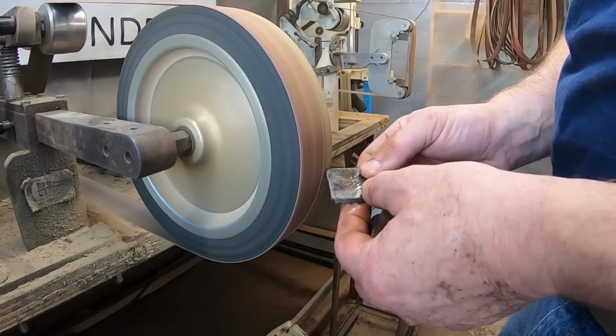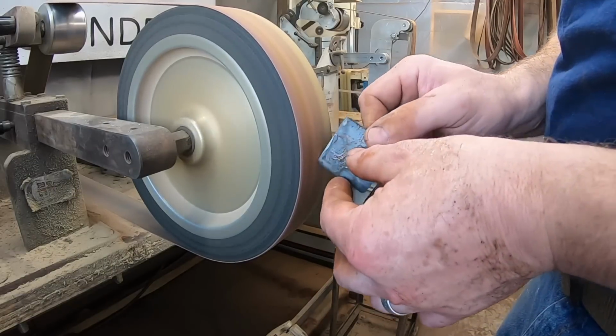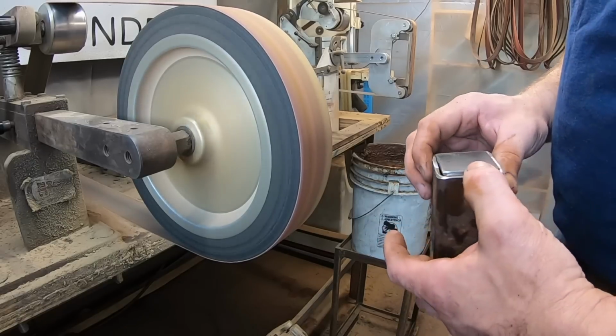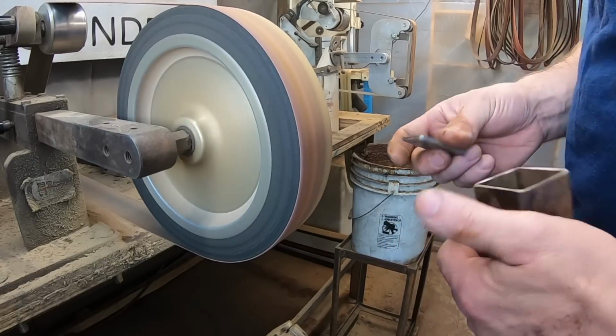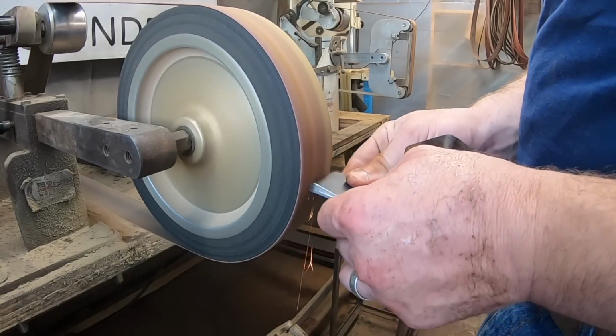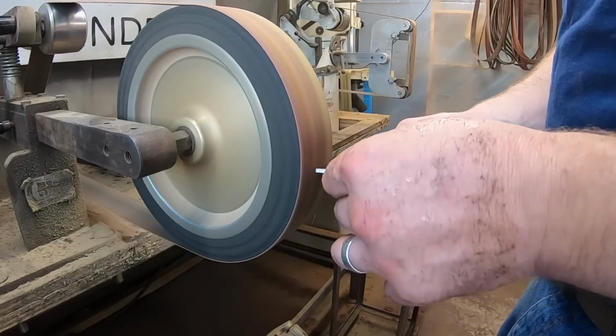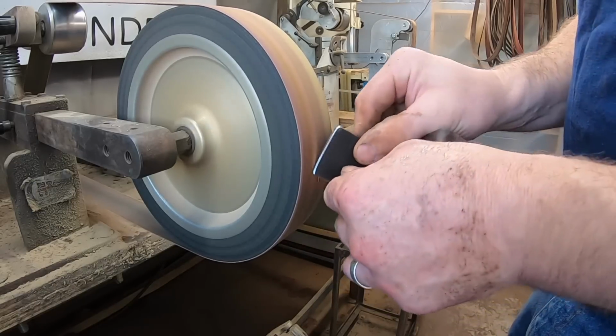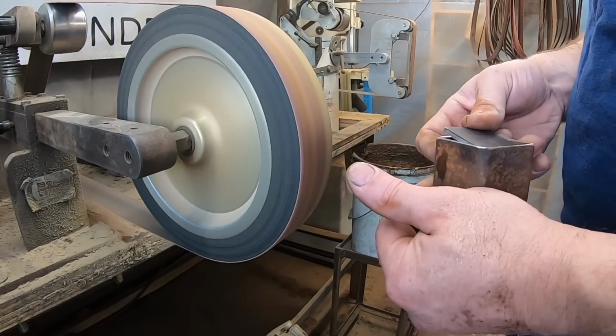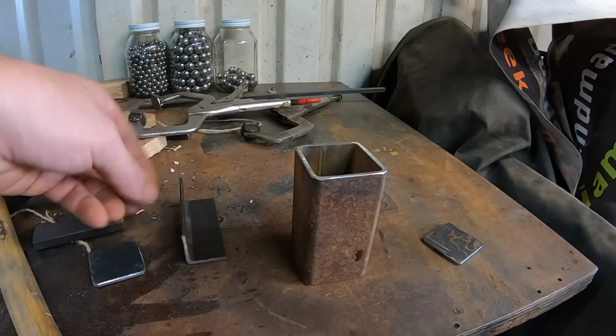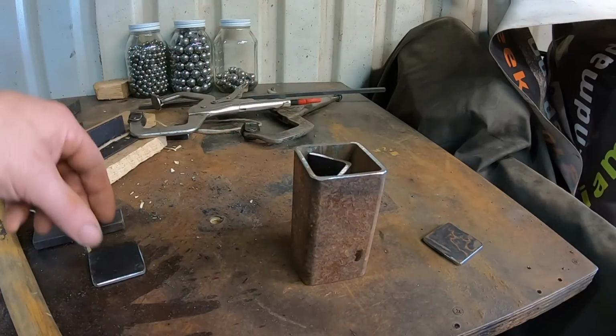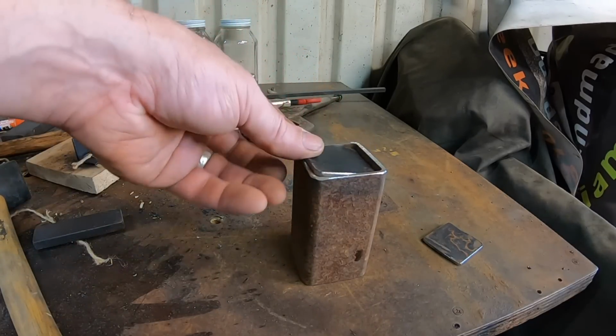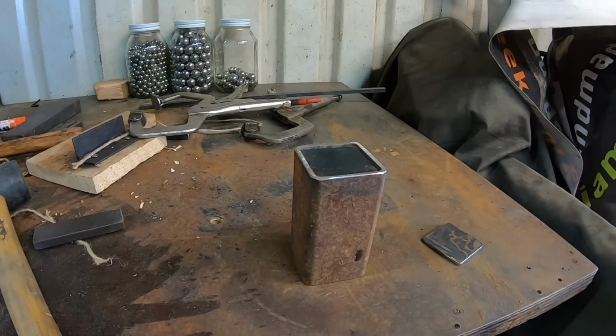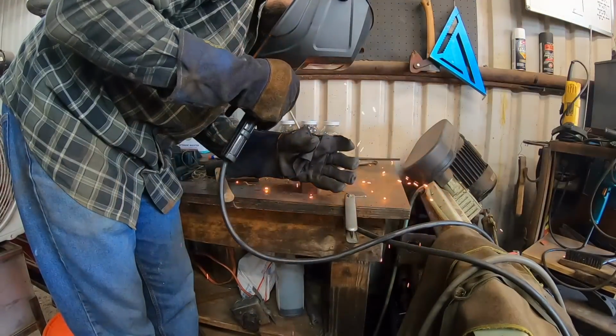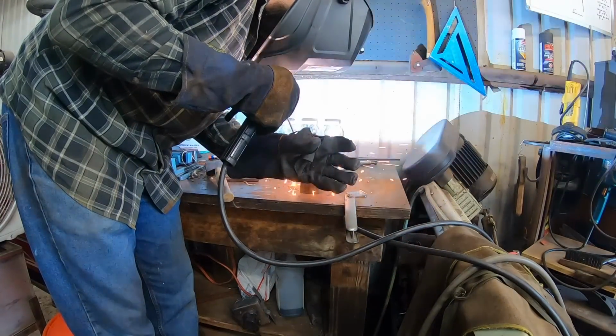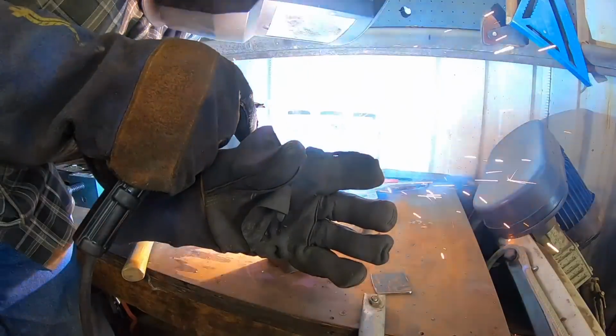I need a couple of mild steel end caps, and they need to fit fairly tightly, but a little bit of gap isn't going to hurt anything. In this case, I didn't get them quite as tight as I wanted to, so I used a little length of angle iron so the cap could just sit right where I wanted it while I tacked it and then welded the seam up with the arc welder. Seemed to work pretty good.